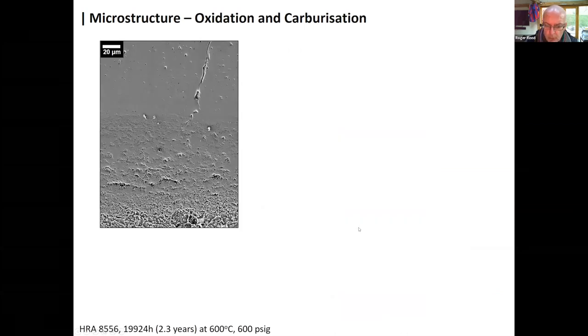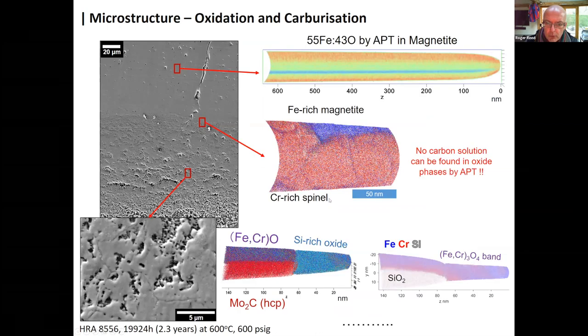So if one looks more closely again, you can see a distinction between the iron-rich and the chromium-rich spinels, and extensive examples of porosity and pores which are close to the interface. We think that this is a mechanism by which the CO2 reaches the metal, because we see very little, if any, evidence of carbon in the oxide phases which are formed. So this leads us to think that the gas is able to reach the interface without too much dissipation of energy.